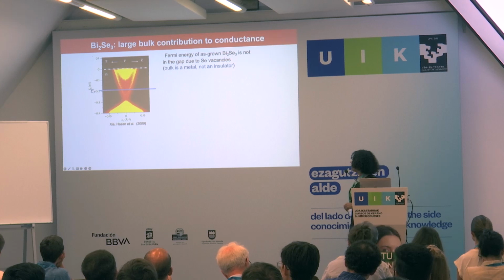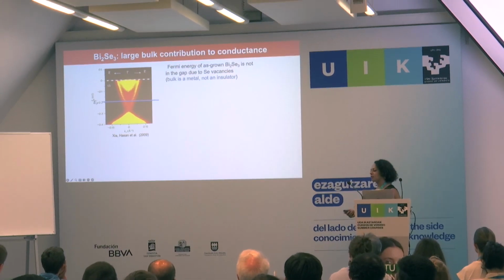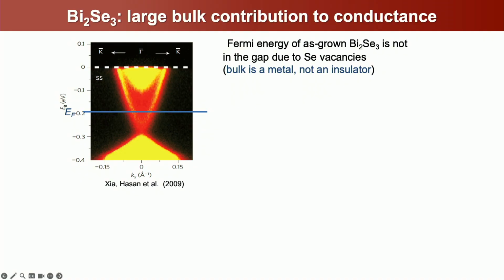bands at all. It turns out for almost all of these materials, unfortunately, the Fermi energy isn't at the Dirac point, but rather somewhere in the bulk due to just vacancies in the system. So most of the times when you want to measure these, you have a metal and not an insulator. And this is a problem because most of the time we want to study the surface states, which have all these interesting properties, but we can't access them because you have a surface state, which is a nice conductor, but then a bulk, which is also a really nice conductor. And so you can't differentiate between the bulk states and the surface states through transport alone. And that's a problem when trying to study these.